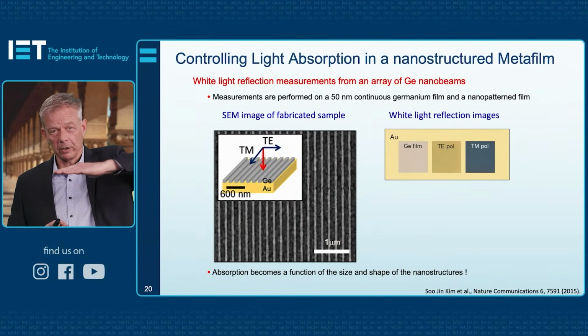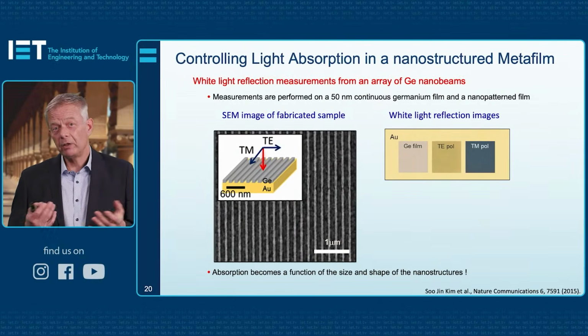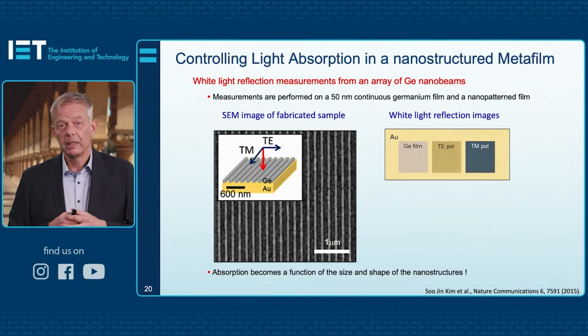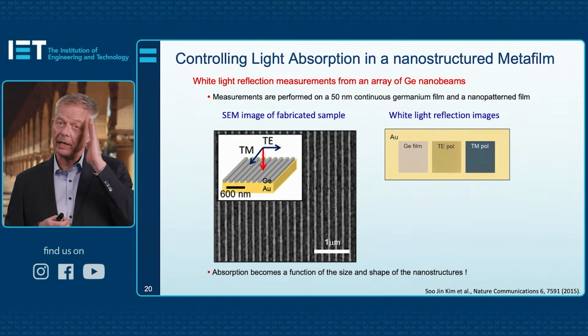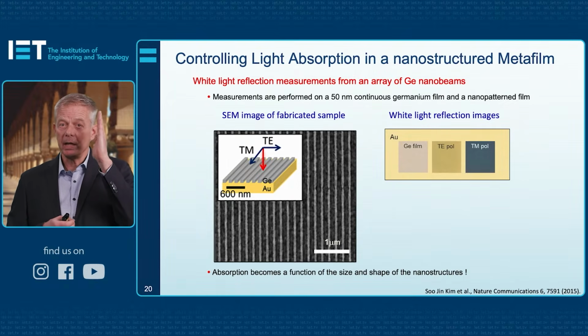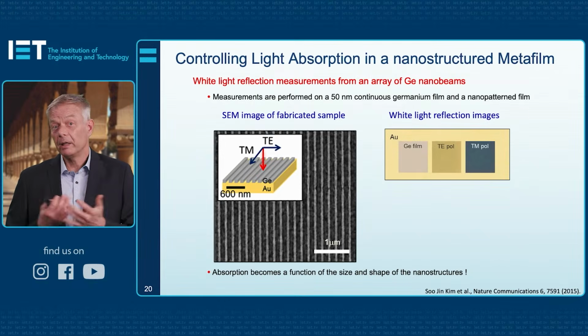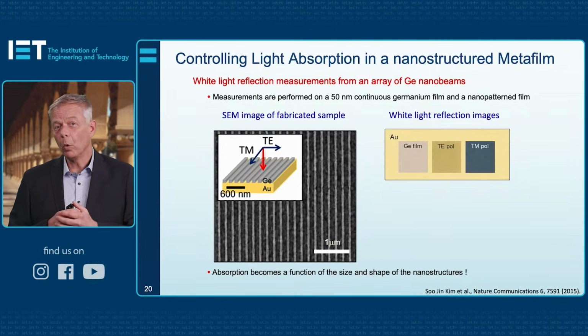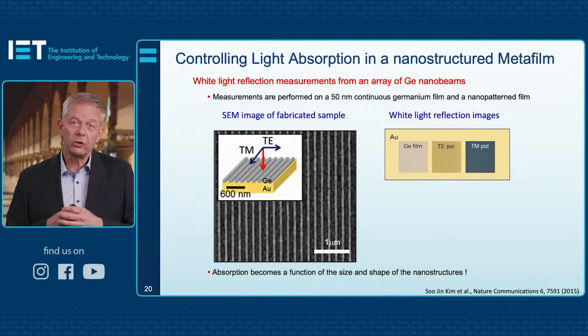And we can illuminate this film with polarized light, where the electric field is either along the wires or orthogonal to the wires. Based on the anisotropy in this sample, you might expect a different optical response if the electric field is along the germanium wires that light up a little brighter than the background, or when the electric field is orthogonal.